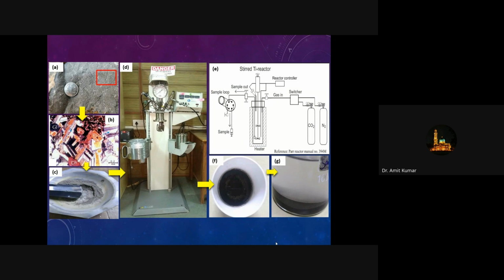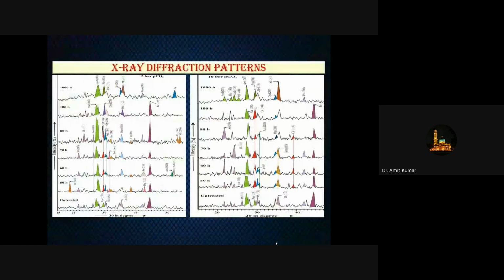After that, we did the various analyses, and the first one is the XRD. In the bottom line, you can see the unreacted basalt, and after that, the 50-hour experiment, 60-hour experiment, and 70-hour experiment. So you can see the formation of carbonates, for example calcite in red color and other carbonate minerals, which were initially not present in the unreacted basalt. So this is the evidence of successful carbon sequestration in Deccan basalts.